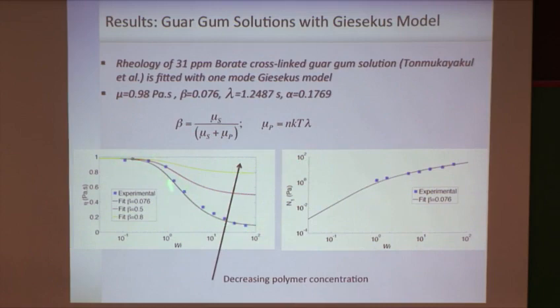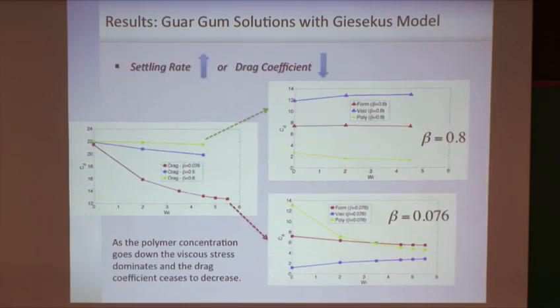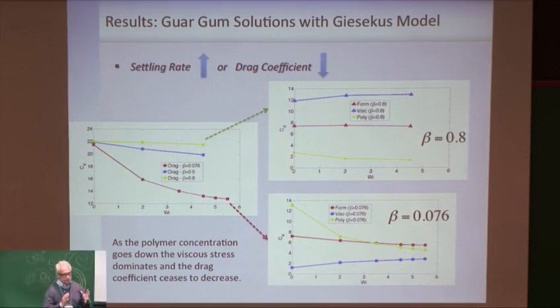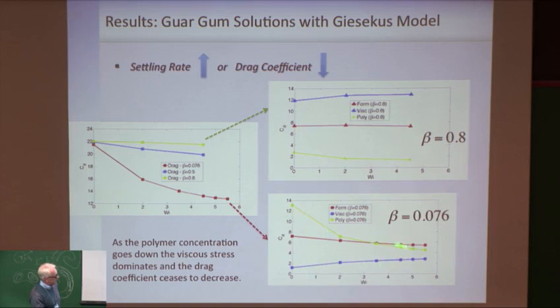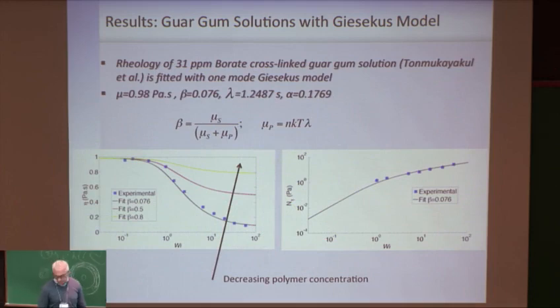Let me just say one last thing. Suppose you take a fluid that's bad. Here's a bad guar gum solution. We can fit the rheology and figure out why it's bad. The moral of the story is the reason it's bad is because there's not enough solvent. Because it's the solvent that's actually increasing the drag. If you add too much polymer, or more specifically, if you add too much polymer stress, the polymer stress, when it dominates, decreases. The viscous stress is actually still increasing, but it's such a small fraction that ultimately the polymer stress wins in this particular fluid case, and the drag coefficient decreases. So the moral of the story is there's a sweet spot in solvent stress versus polymer stress that tells you what's a good fracking fluid and what's a bad fracking fluid. If you believe this, then it's the viscous stress that's actually creating the increase in drag, and you've got to have enough of that with an indirect polymer contribution to the flow to create these increases in drag coefficient.